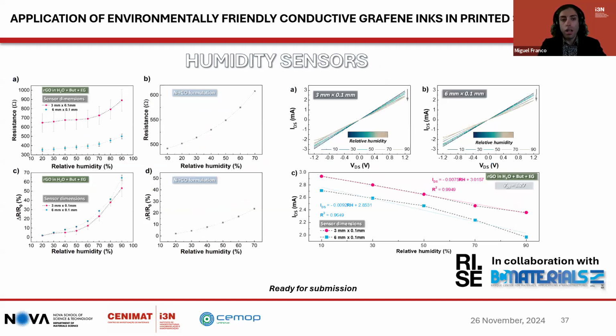The sensors can achieve a change of resistance up to 4.25 ohms per percent change of relative humidity when used as a resistive sensor, or 0.19% per percent of relative humidity in change of current in GFET mode, while also showing good linearity. The major advantage of using conductive reduced graphene oxide based sensors is their readability in resistive mode and fixed low impedance. This allows the possibility of incorporating these sensors in low power commercially available microcontrollers for sensing applications, thus eliminating the need for complex impedance and capacitive measurement systems.